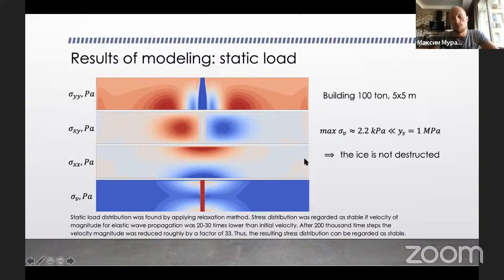So the maximal von Mises stress was equal to about 2 kilopascal. That is significantly less than the limit of shear stress, which is equal to 1 megapascal. So the ice island is not destructed in such a problem. Static load distribution was found by the relaxation method. After 200,000 time steps, velocity magnitude stayed on about the same level, so the resulting stress distribution is stable.